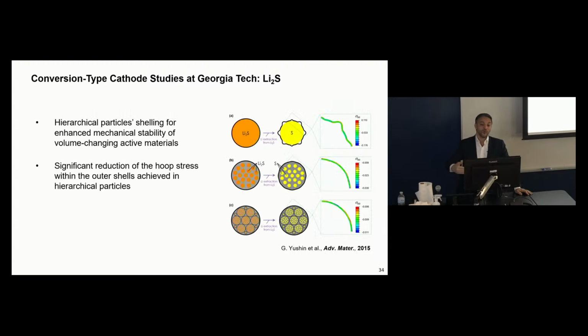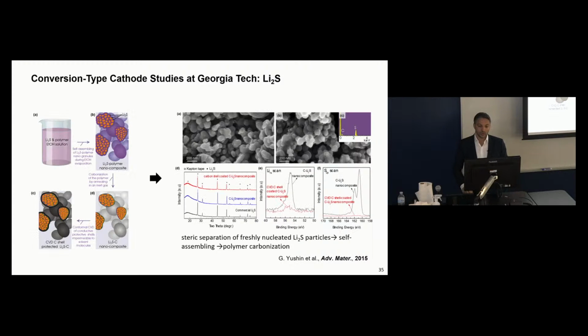And so another way to overcome it is to design these hierarchical particles, where you have multiple levels of protection and nanoparticles immersed in some sort of matrix material. In this case, the overall volume changes are smaller, right? So you can prevent cracking of the shell during charge or discharge. And you can also minimize the probability of this polysulfide formation and leakage into the electrolyte. And so there are multiple ways to do it, but we developed a very simple methodology some time ago.